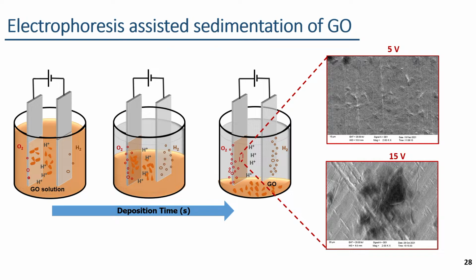After that, the morphology of these GO coatings deposited under different voltages was measured using SEM, that is scanning electron microscopy. These are the SEM images obtained at high and low voltages. During the EPD process, the change in GO concentration within the electric field region shows a dominant effect on the coverage of these GO coatings due to the sedimentation process. However, at higher potentials, delamination of these coatings due to the evolution of gas bubbles with water electrolysis limits the growth, homogeneity and stability of these GO coatings.